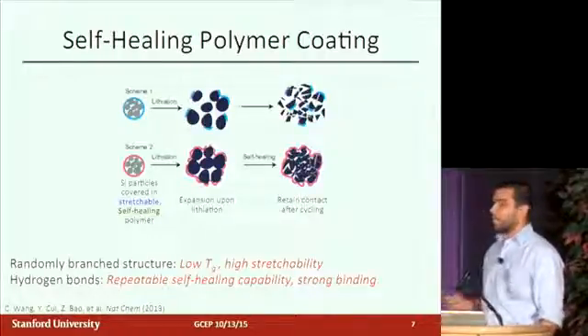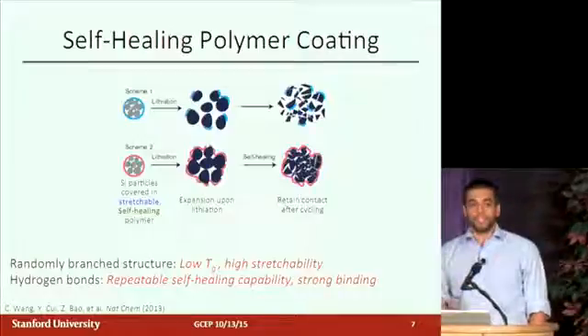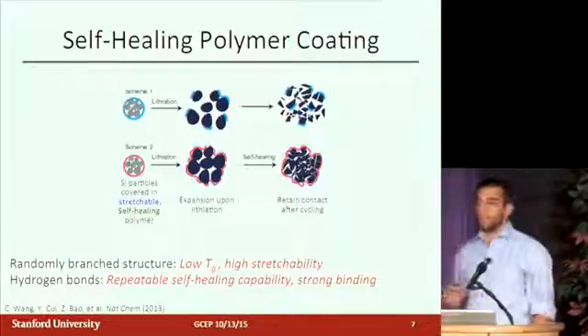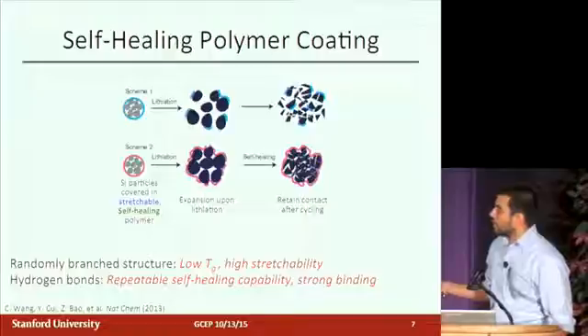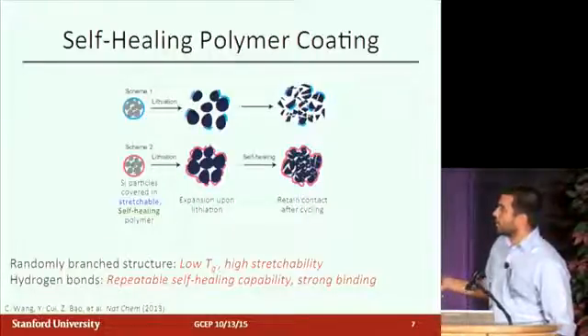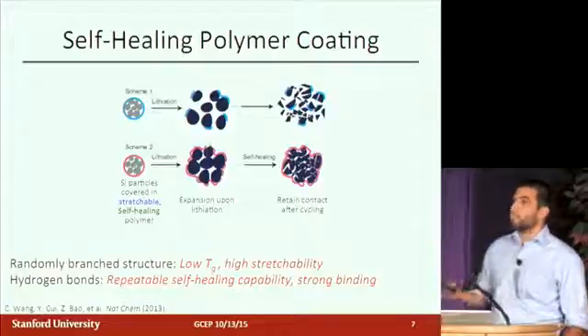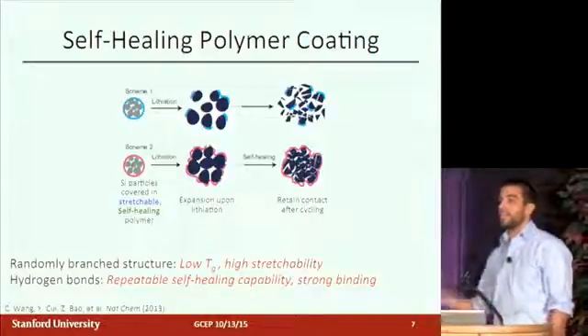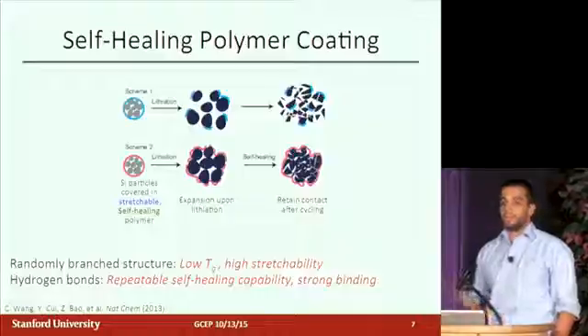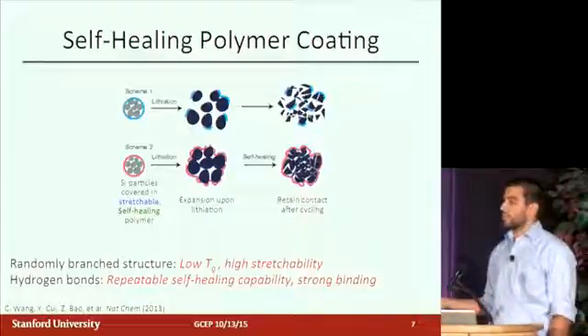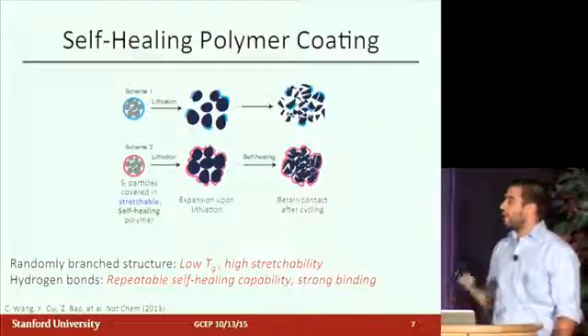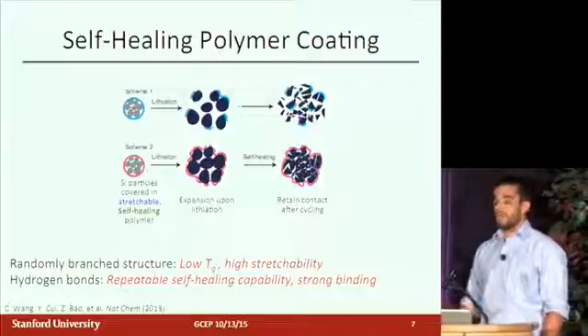But with our self-healing polymer, we design it to be highly stretchable and a little bit flowable at room temperature as well. We think that as the silicon expands, cracks will form, but then as those cracks form, the self-healing polymer will allow those cracks to heal, and it will fill in any new surface area from the silicon, so you're really eliminating both of the mechanisms of failure in these silicon electrodes. One, again, is the electrolyte decomposition reaction on new surface, and the other is just mechanical failure of the electrode.